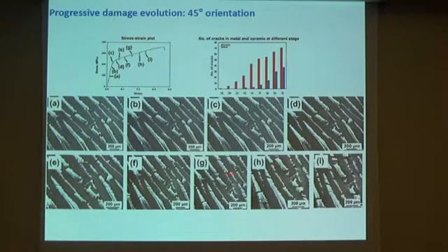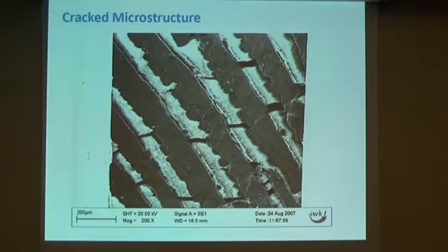And if you look at photographs, say F, G, H, and I, you will see cracks appearing in ceramic layers. And this is a figure giving you a summary of the number of cracks in metal and ceramic layers at different stages. So let us focus now on one of such photographs and have a closer look at these cracks. Whiter layers are ceramic and gray layers are metal, and we see cracks which are spaced at some distance from one another, and some of these cracks look more like gaps, so it is not a mathematical section but rather like small holes. So all of this was our motivation for modeling.